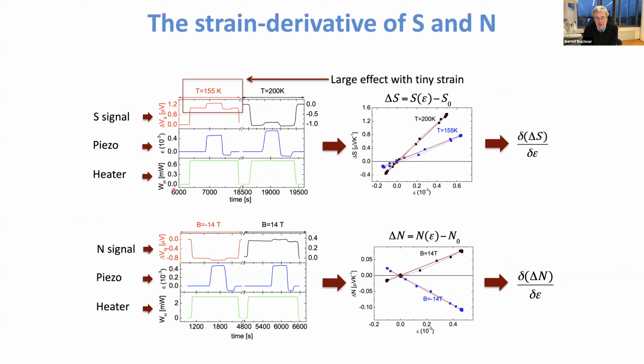So we switch on a heater. The heater induces Seebeck, the thermal power. So you see a voltage. Then we switch on the piezo and you see a change of the Seebeck effect, switch off the piezo again and the heater. So that's then the strain dependence of the Seebeck effect. And that's here measured at a different temperature, and you see the Seebeck effect is negative and the strain effect is still positive. So you can really discriminate these two things.